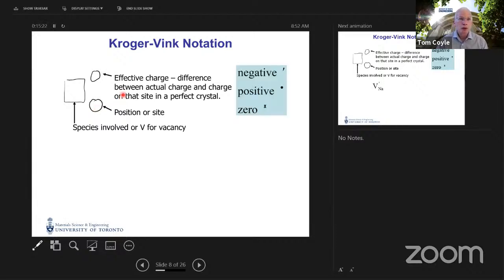And just to help us remember what we mean by the effective charge, we don't use a plus sign or a minus sign. We use this apostrophe sign to represent a negative effective charge, a dot to represent a positive effective charge. And if the charge on that site is what we expect it to be, what it ought to be in the perfect lattice, then we use a little X to represent the fact that the effective charge is 0. And remember, that doesn't mean that the charge associated with that site is 0. It means that the charge associated with that site is what we would expect it to be in a perfect crystal.